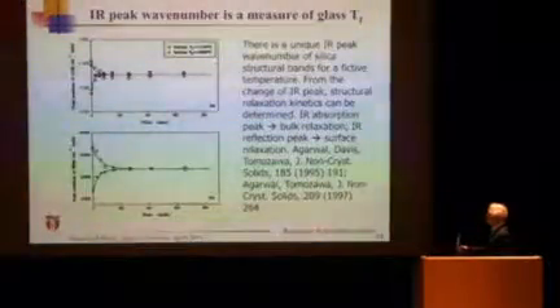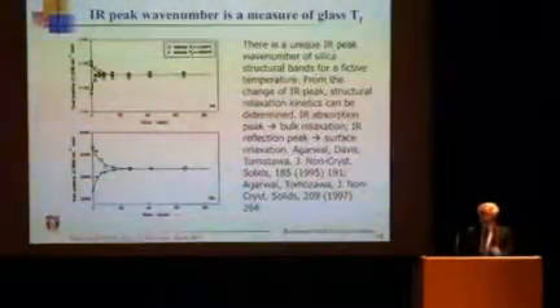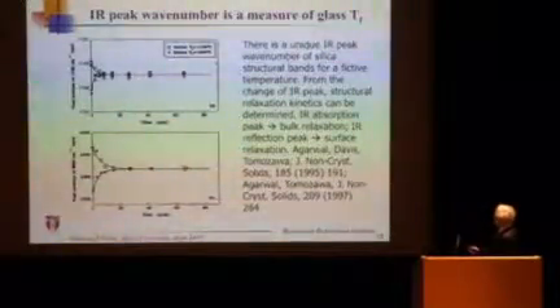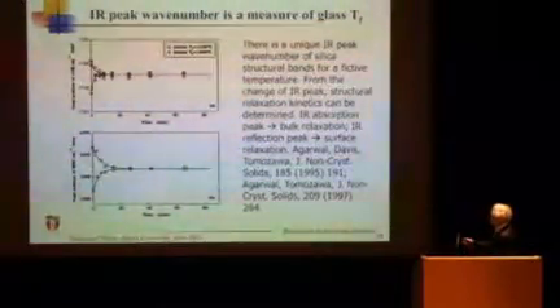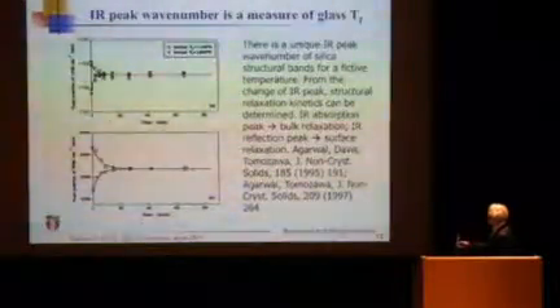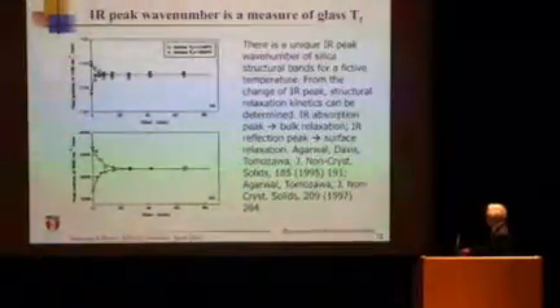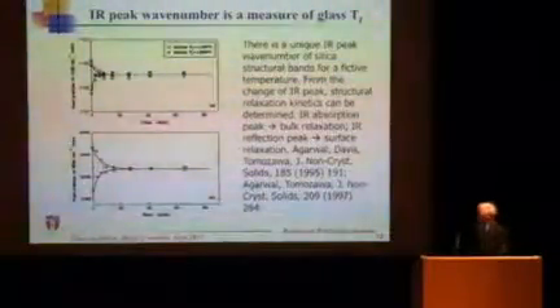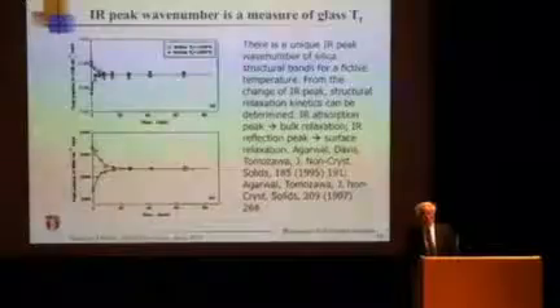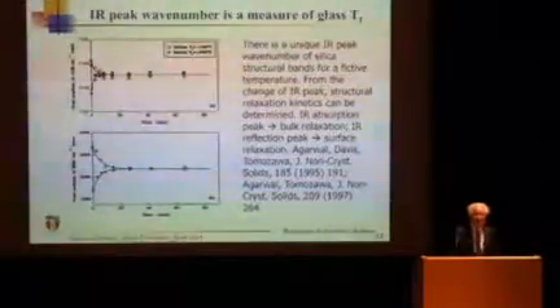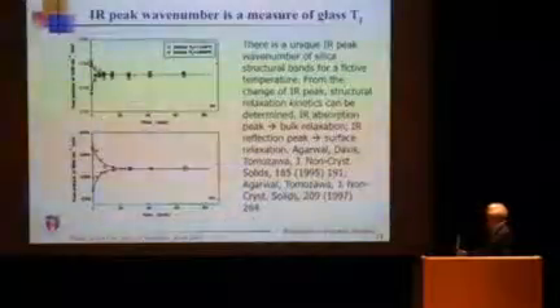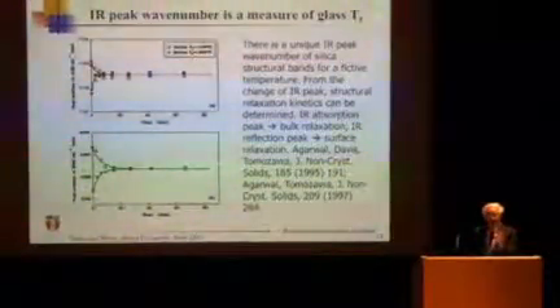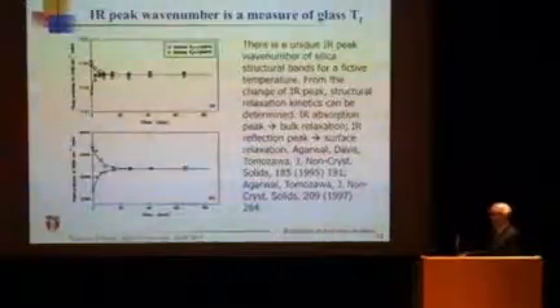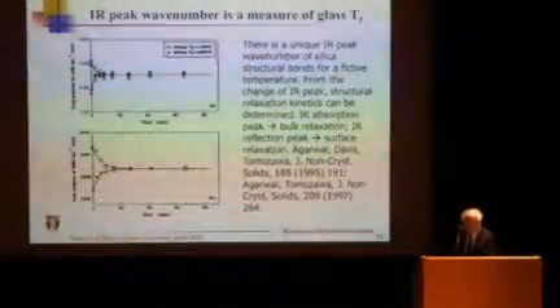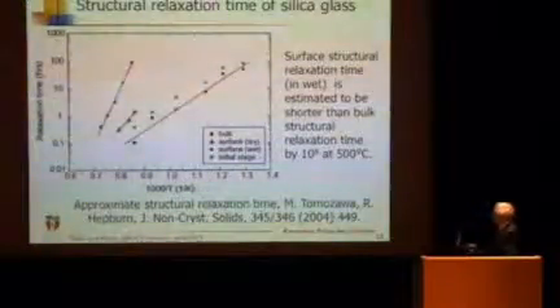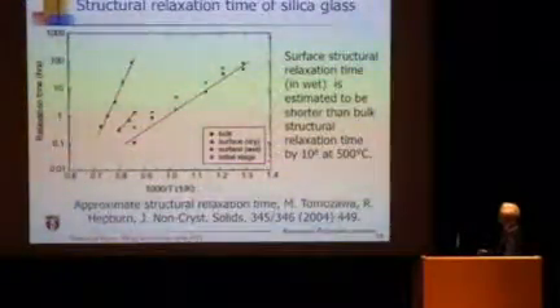This was measured by reflection, measuring a small thickness of the surface. And this suggests to me that the surface layer, which is probed by reflection, is changing more quickly, on the same time scale, than the bulk transmission measurement. This fictive temperature change is called glass structural relaxation. So immediately we realized this is telling me the surface structure is changing faster than the bulk. This is something new we found, and we measured the relaxation time of silica glass as a function of temperature.